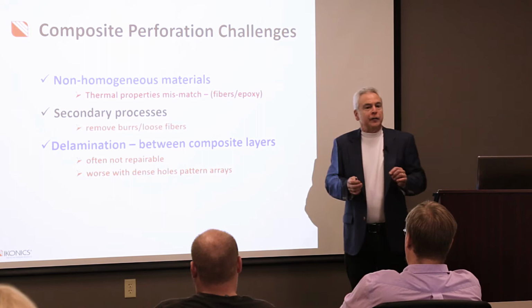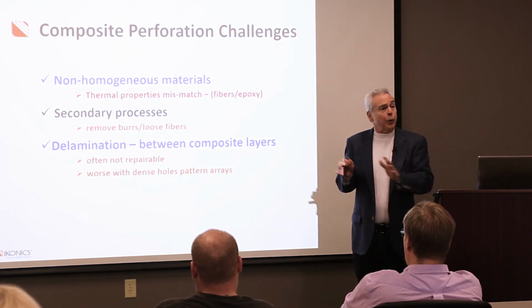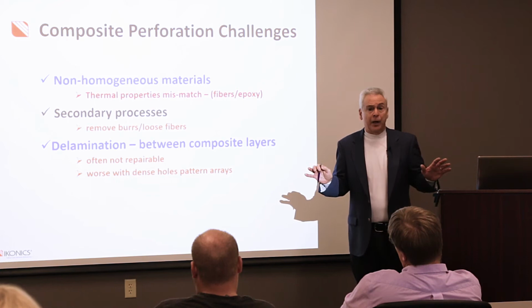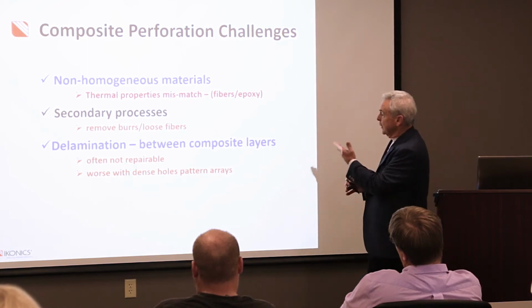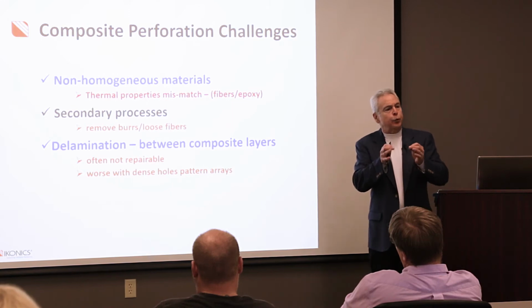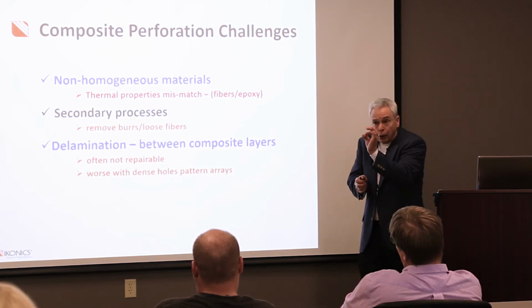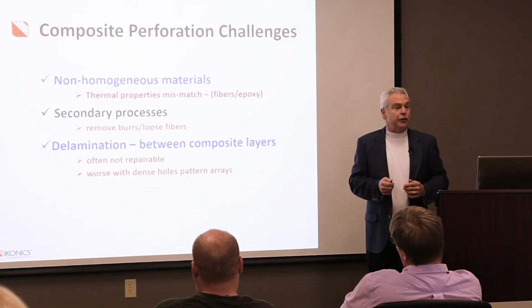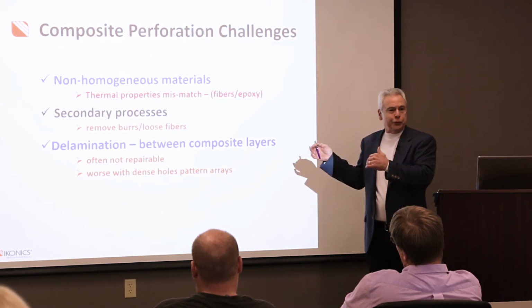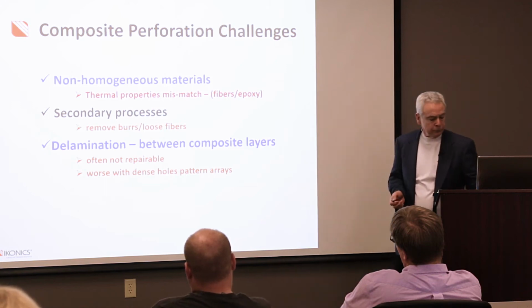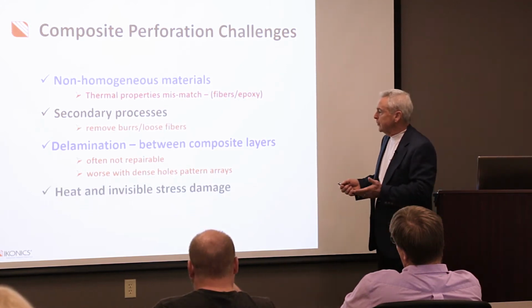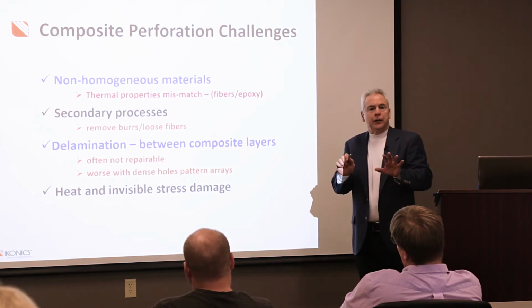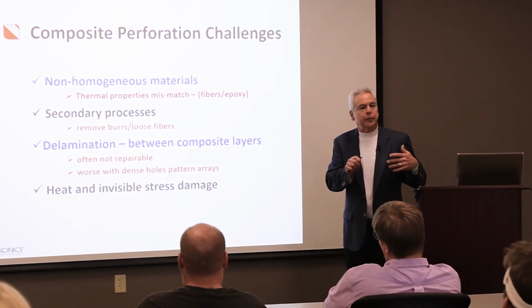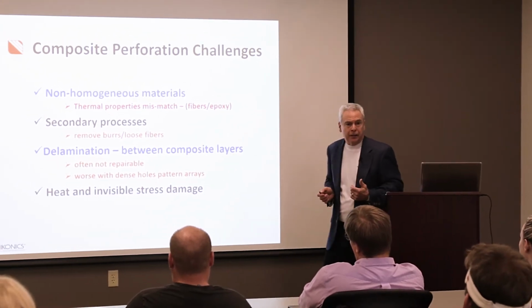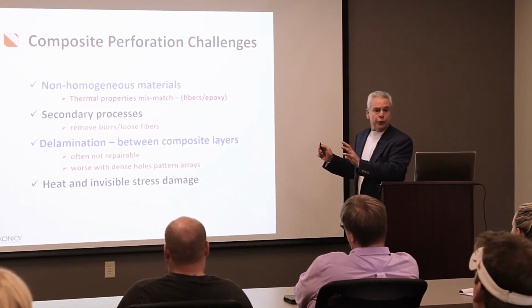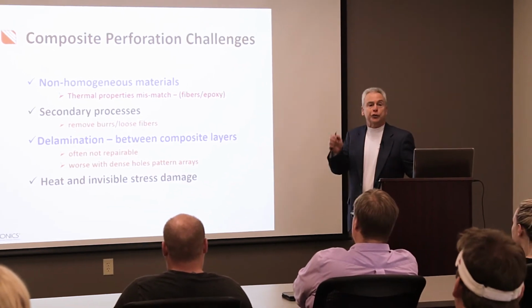Delamination between composite layers is an extremely challenging issue because when that occurs, you don't repair that composite. You essentially throw it away. So that's really a major issue. And as they get more dense with the holes that are put in during perforation, in other words, holes are closer together, that tendency for delamination becomes even more critical with the traditional methods for machining. And last but not least, heat and invisible stress damage. This is something you don't normally see until after the composite has been perforated and then it's been tested. So these are challenges, if you will, associated with perforating composites with traditional methods.